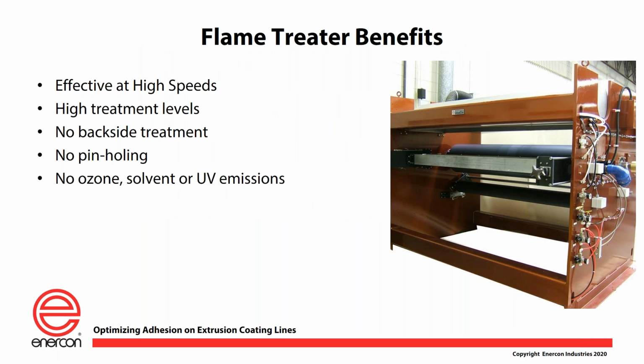Well, the benefits of a flame treater, and a lot of times, if you're not familiar with the flame treater, you probably don't want to use it. It is a little more complicated than a simple corona treater, but people use it specifically for paper applications and very high line speeds so that you can get a higher treatment level. You can avoid backside treatment, which is caused by having air trapped behind the web and the roll. You avoid pinholing the film, and you don't have to worry about ozone or any kind of other solvents or UV emissions that may occur when you have a plasma treater or corona treater.